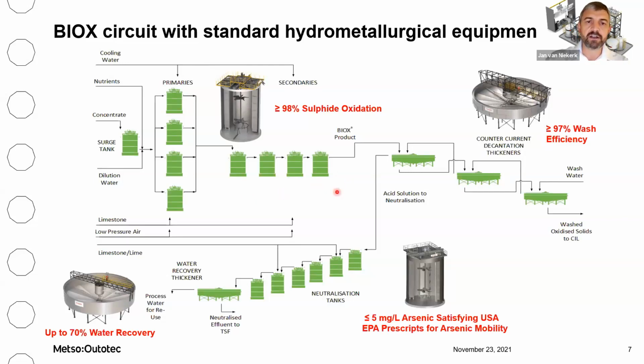During the BIOX process, the iron, sulfur, and arsenic is solubilized during the oxidation of the sulphide minerals. So following BIOX, a 3-stage CCD circuit is used to wash the BIOX product and ensure that you've got a clean oxidized solid slurry that is then fed to a standard CIL circuit. The dissolved iron, arsenic, and sulfur that is now in an acidic solution is neutralized in a 2-stage process using limestone and lime to produce stable ferric arsenate precipitates that can be deposited onto a tailings dam. As you can see, the process is simple and uses standard equipment, atmospheric reactors and thickeners.